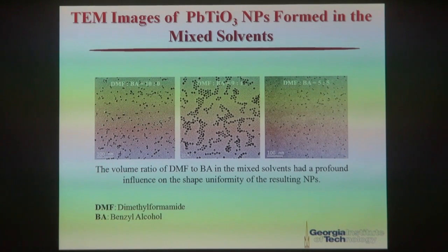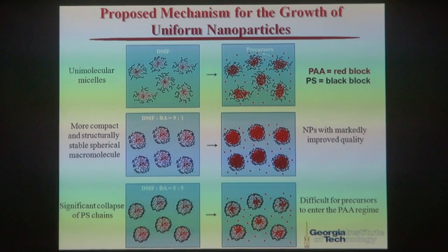Why is that? Actually, all this can be understood by considering the solubility of polymer chains in these mixed solvents. So when DMF is the only solvent used to do the reaction, we know DMF is good solvent for both inner PAA block in red and PS block in black. So we have this fully expanded polymer chain conformation. Polymer chains are fully stretched in DMF. However, when you add 10% benzyl alcohol in the system, we know benzyl alcohol is the poor solvent for outer polystyrene block. However, it is still a good solvent for inner PAA block. So at this particular DMF to benzyl alcohol 9:1 ratio, the outer polystyrene block actually collapsed a little bit. Now you have transition from fully expanded polymer chain conformation to these more compact, structurally stable spherical macromolecules.